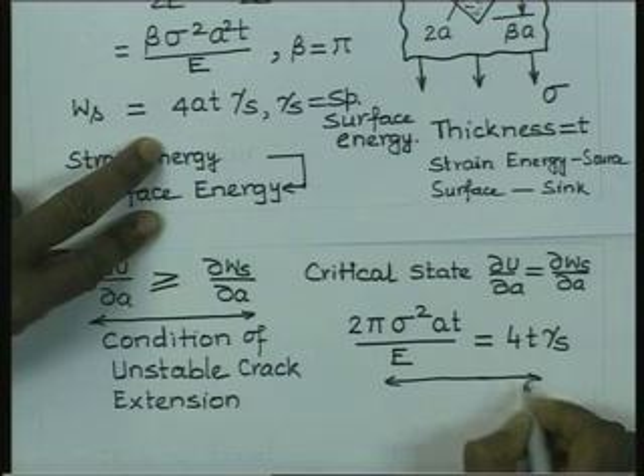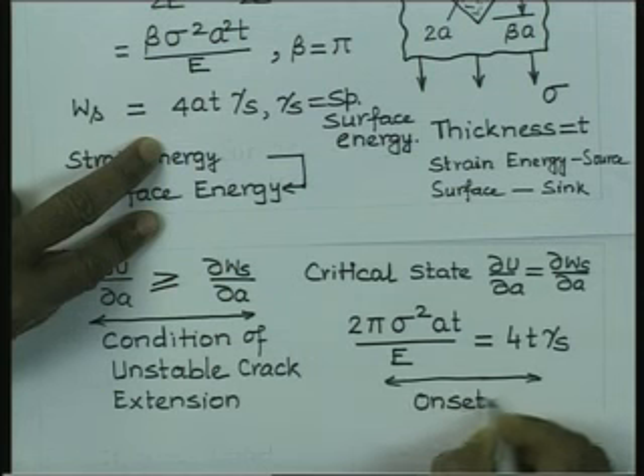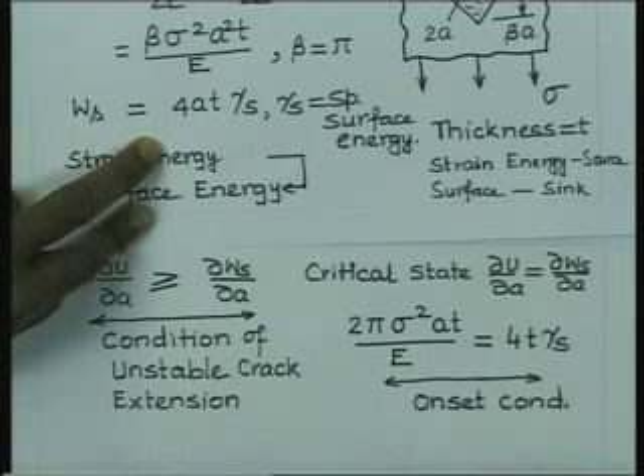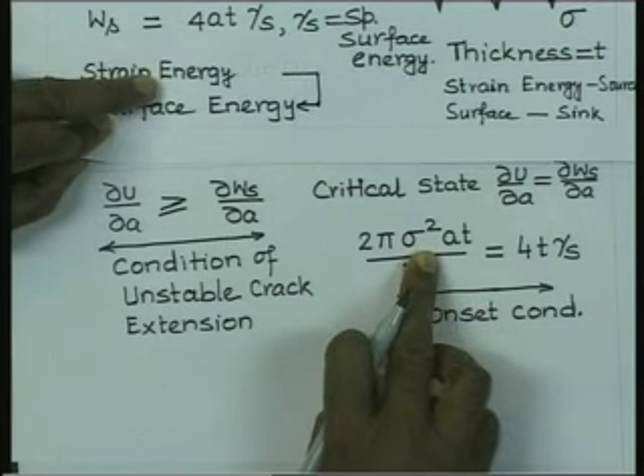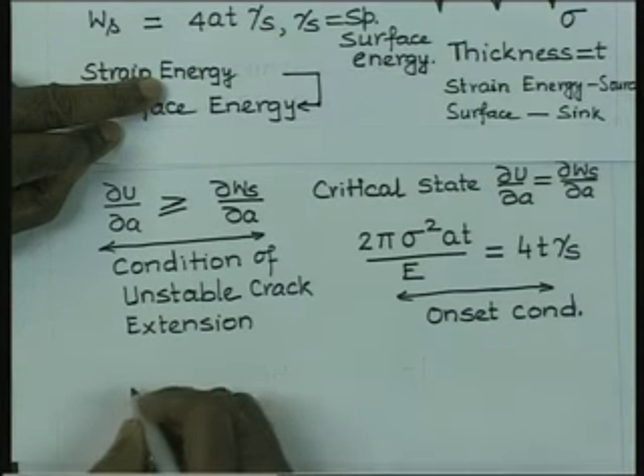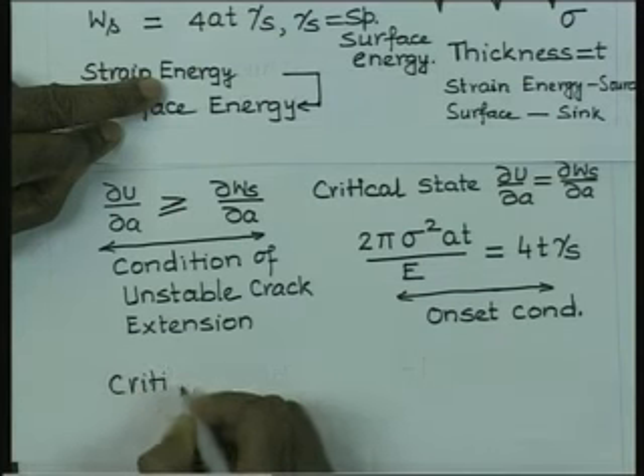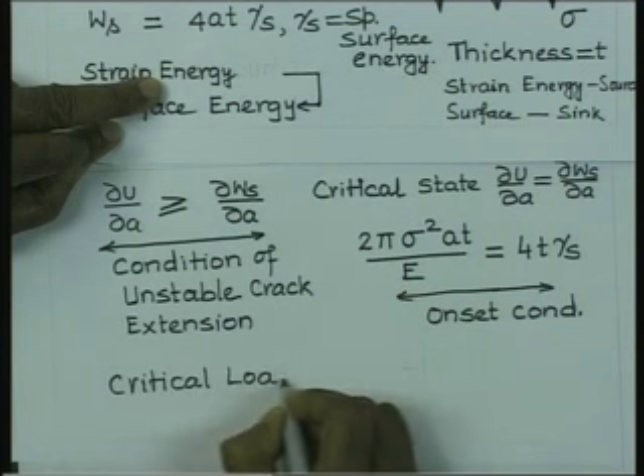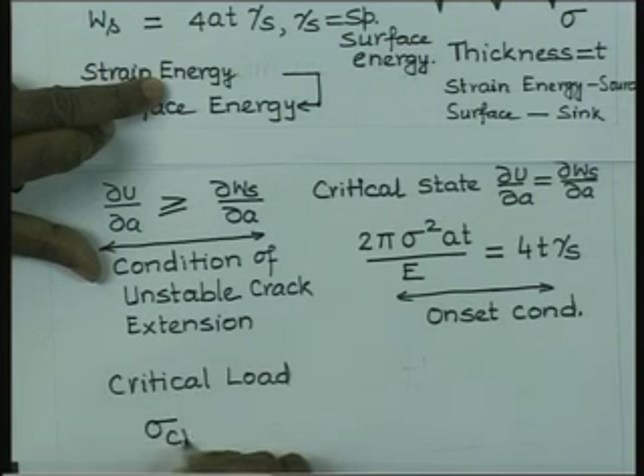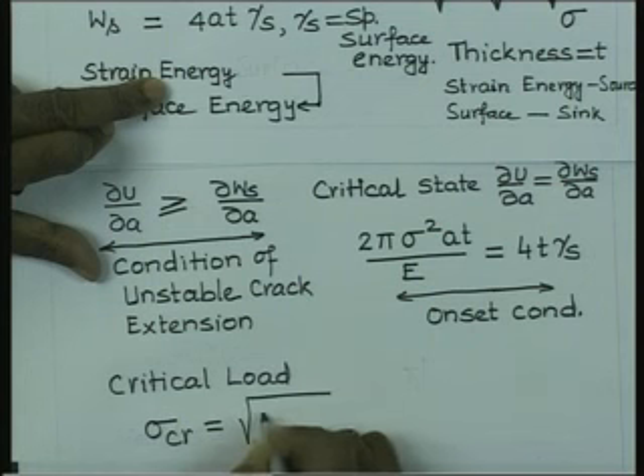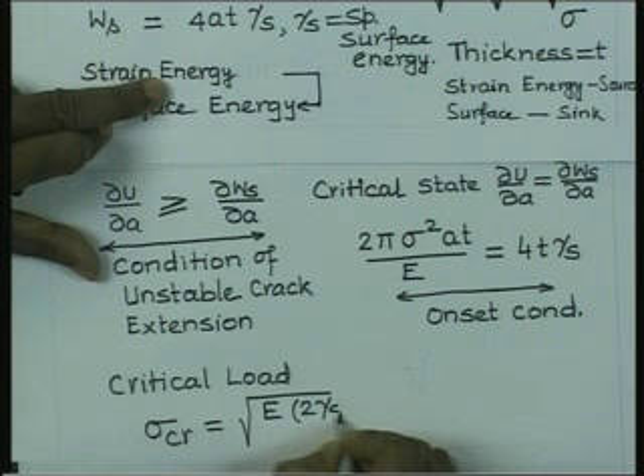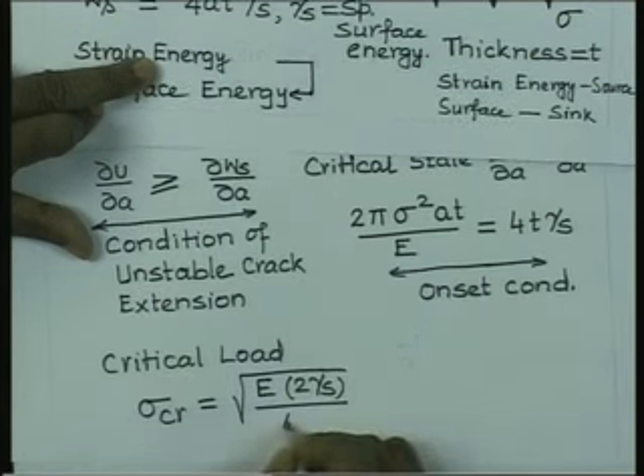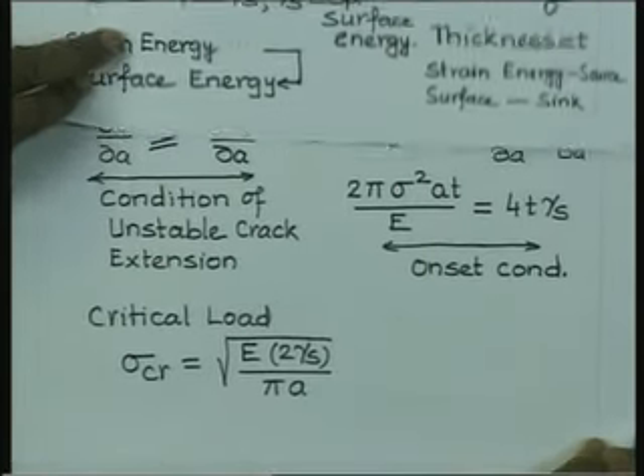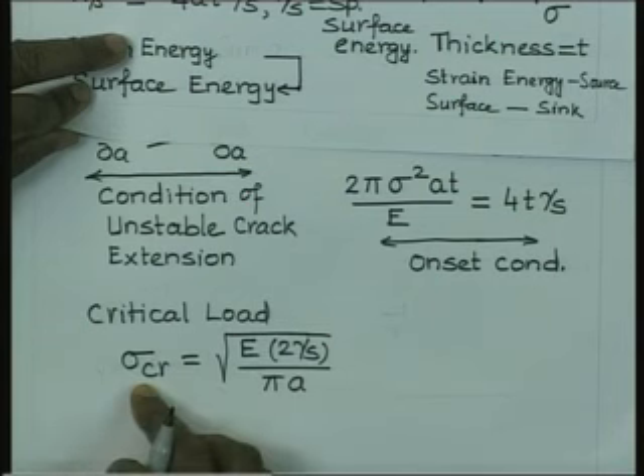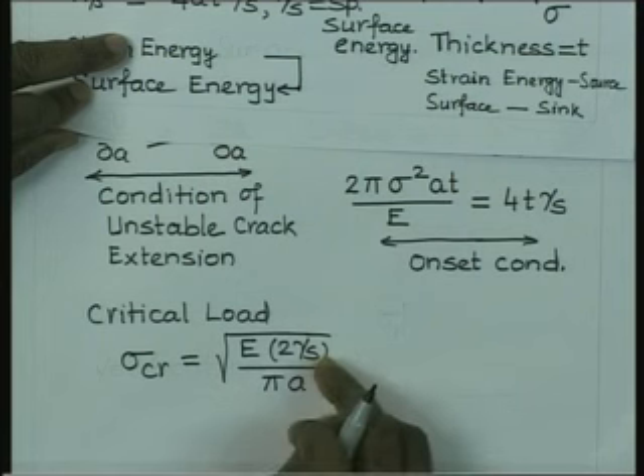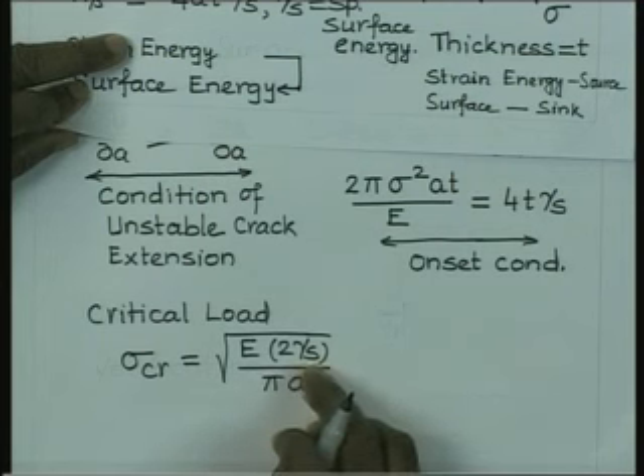So, this is the onset condition, and therefore, it gives you the loading which will trigger the extension. Therefore, the critical load, sigma critical, is given by the square root of E into 2 gamma s by pi into a. So, this is a very important relationship. It gives you the critical stress which will trigger the extension of a crack in a material with surface energy capacity equal to gamma s.